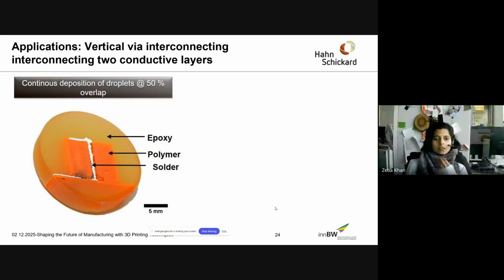The next application I show you is the vertical via interconnections. This is suitable for connecting multiple layers. Here you see a continuous deposition of droplets produced at 50% overlap, so each droplet was overlapping with the other droplet at 50%. In this image, you see the solder in the silver color, the polymer in the orange, and the epoxy in the yellow. This ground sample was done to observe what the metal on metal bonding looks like, because this was a layer by layer printing.